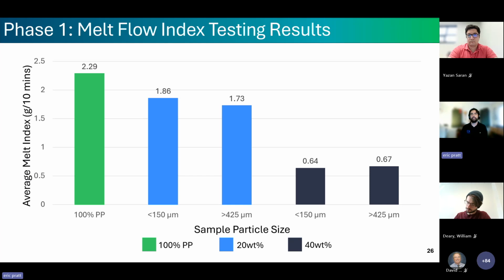Finally, melt flow index. Again, this is simply a measurement of processability. Relative to a 100% polypropylene baseline of 2.29 grams per 10 minutes, our 20 weight% loading samples dropped the melt flow index by 18%. And that's essentially our processability ceiling, since anything much beyond 20% drop risks becoming unworkable on existing equipment.